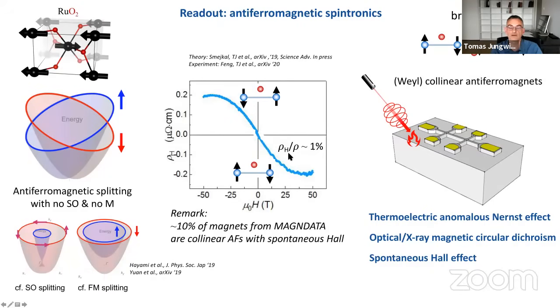Again, the size of the effect is comparable to these simple film magnetoresistance signals, of the order of 1%, which compared to the anomalous Hall effect in other systems, including ferromagnets, is large, but remains on the order of 1%. Also, these collinear antiferromagnets can host the topological Weyl-like features in the electronic structure, but one again needs to find the ideal material system where these would lead to the singular behavior of the anomalous Hall effect.